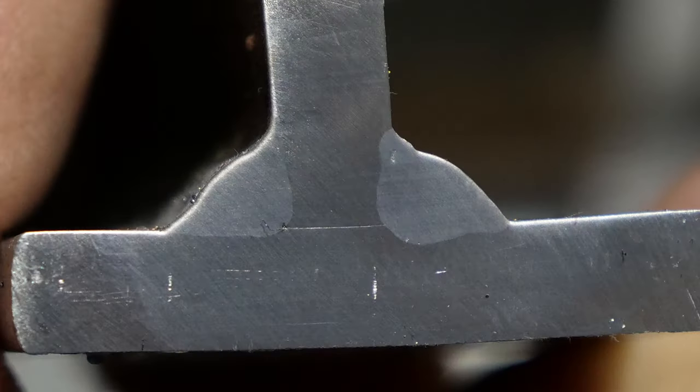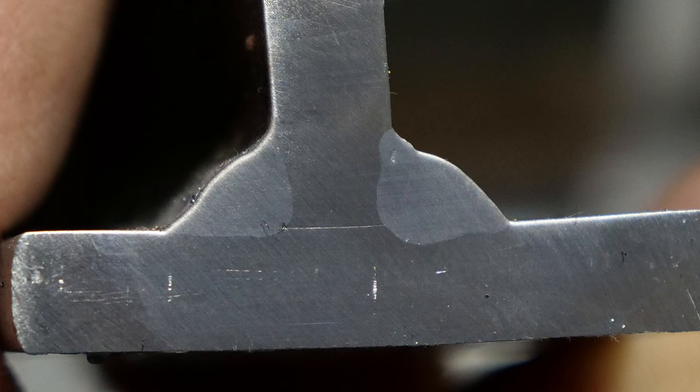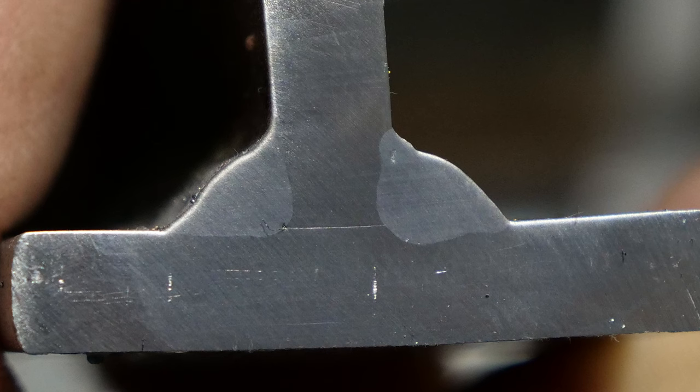This is 6.5 millimeter rough plate, quarter inch. The weld on the left was short arc MIG, the weld on the right is flux core. Obviously the flux core has way better penetration on this thicker plate. The short arc MIG weld, you can see that intersection line where the top plate meets the bottom flat plate, and basically there's no root fusion whatsoever at that point, which coincides with my previous video.